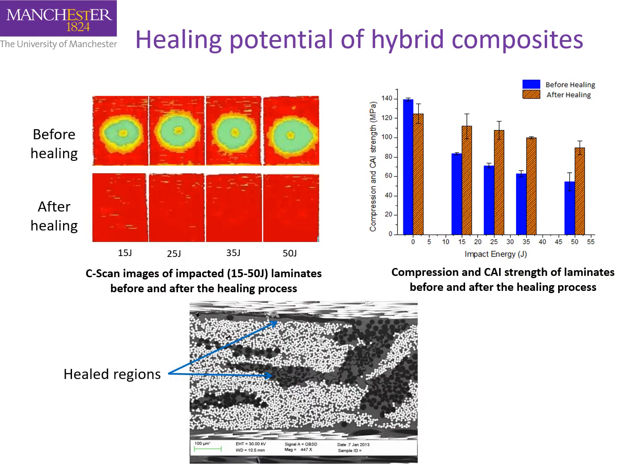And when eventually damage does occur, upon heating the laminate, all the matrix cracking and delamination introduced during the impact can be filled up because the polypropylene fibers melt and fill those gaps. By repairing or self-healing those cracks, the laminate has recovered much of its original strength and stiffness.